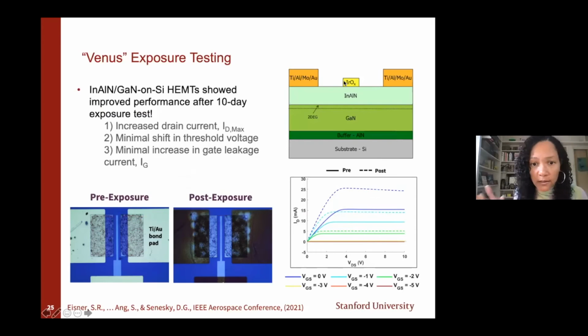Also, our off current has a slight increase, but very negligible. On-off ratio is roughly the same. Also, our threshold voltage is really staying pretty stable. And then also slight increases in our transconductance and subthreshold swing. So what that tells us is that this is working. This is a 10-day test. And so this is, in some ways, working better than it did before.